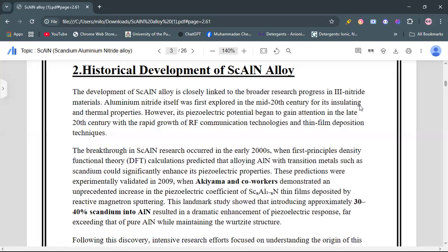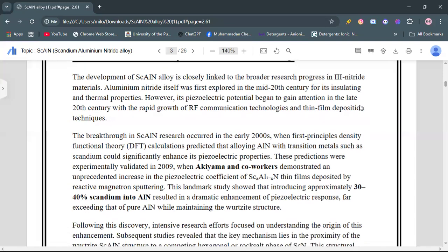The breakthrough in scandium aluminum nitride research occurred in the early 2000s when first principles density functional theory (DFT) calculations predicted that alloying aluminum nitride with transition metals such as scandium could significantly enhance its piezoelectric properties. These predictions were experimentally validated in 2009 when Akiyama and co-workers demonstrated an unprecedented increase in piezoelectric coefficient of scandium aluminum nitride thin films deposited by reactive magnetron sputtering.